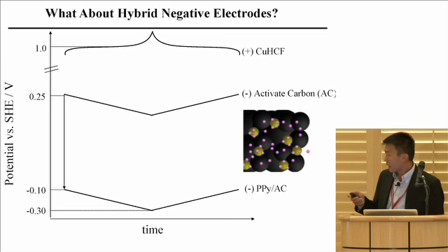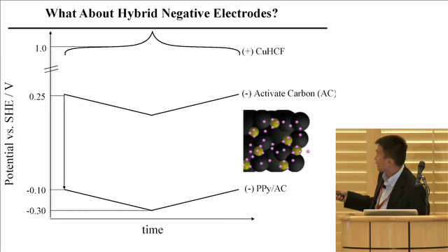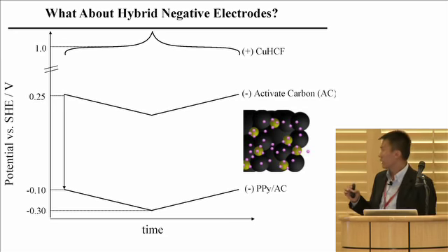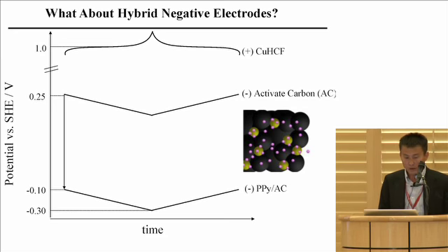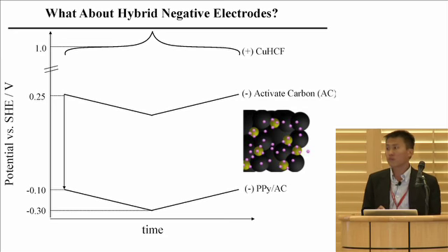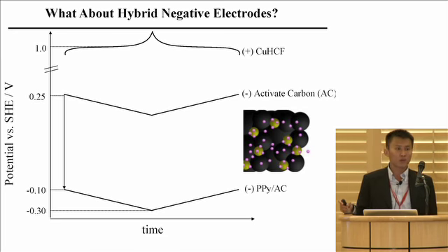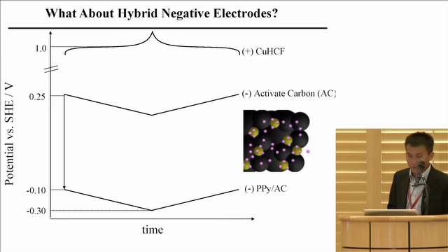Now we find out when you do the CV measurement, if you use the oxidation state of 2 to 3, you now can have materials with potential that's 0 versus standard hydrogen. It turned out this one also has very fast kinetics when you do charging and discharging, virtually no voltage hysteresis, very fast materials. We are making a full cell right now to test out the performance of the whole battery.